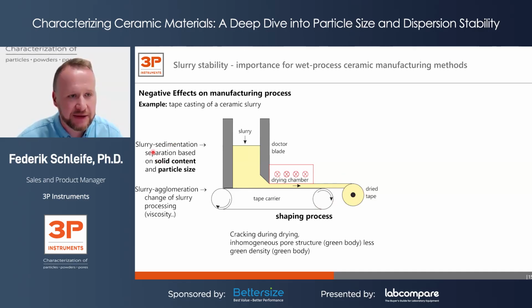But you can imagine if the slurry would sedimentate, you get a separation based on solid content and particle size. That means at the beginning of the process, you will get a lot of large particles, and later on finer particles, which leads to an inhomogeneous dried tape during the shaping process. And also when it comes to slurry agglomeration, there's a change in the slurry processing. Maybe the viscosity might change during the process, which also leads to inhomogeneous processing.